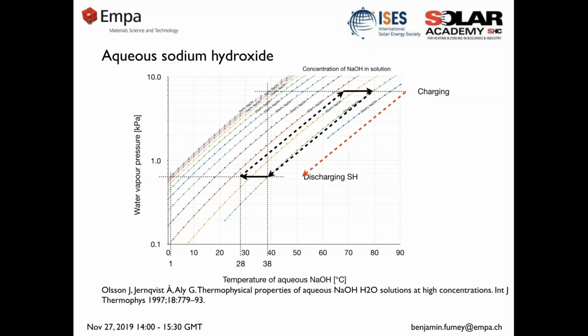the gross temperature lift that I require for the charging, which is the upper line, and the gross temperature lift that I'm able to reach in the discharging, and of course, very important in the discharging also, the minimum concentration that I will get, which then defines my maximum energy density that I can reach. Here, just to point out, you see in the red dashed line is the fact that in our case with sodium hydroxide, we do not want to go beyond 58% because we have a liquid sorption system, and sodium hydroxide tends to crystallize above 58% at room temperature.